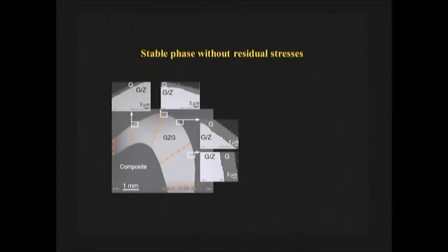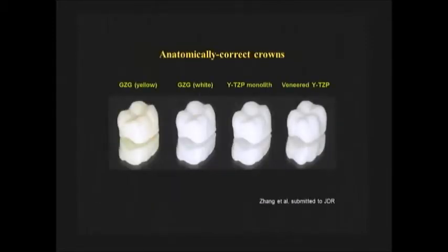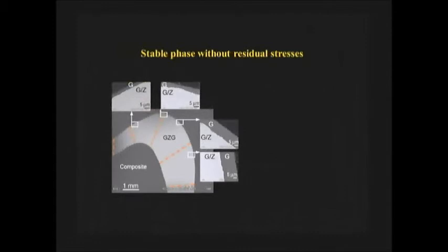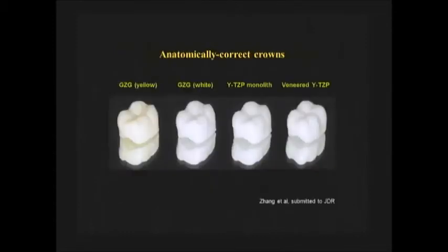The last thing I'm going to talk about is perhaps more for Thomas and Jason and Bob, because we know that you CAD-scan the material, now you have the anatomically correct shape. By the time you infiltrate glass into it, would you cause two problems? One is phase transformation of the zirconia, and two is would you introduce residual stresses into the material? So what we did is we took one of those crowns. In fact, it was one of those yellow crowns. I go back. We cut